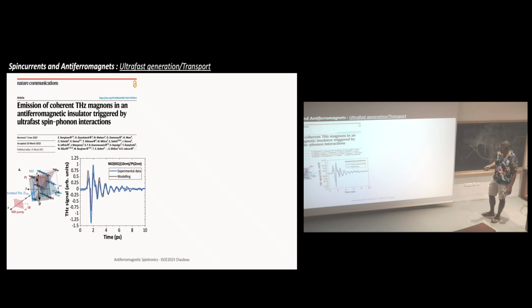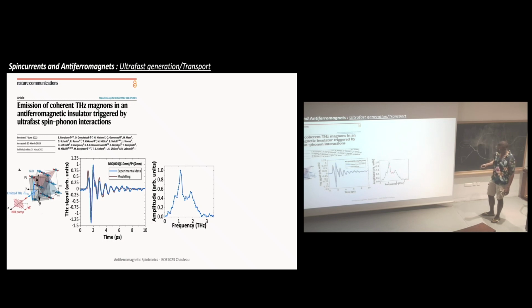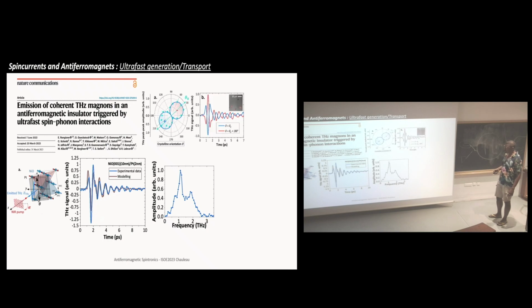And very recently, there was another paper. This time they tackle the same thing. They do the same experiment on a different sample. It's still NiO, but it's in a different sample. And what they see is a very nice oscillation. And if they Fourier transform this oscillation, they see a nice peak at 1 terahertz. To be honest, I've not really understood what this second peak is, and I think in the paper it's not really mentioned, but it will probably come later. But anyway, you have this very nice 1 terahertz oscillation. And on top of this, you still have some kind of broader band.